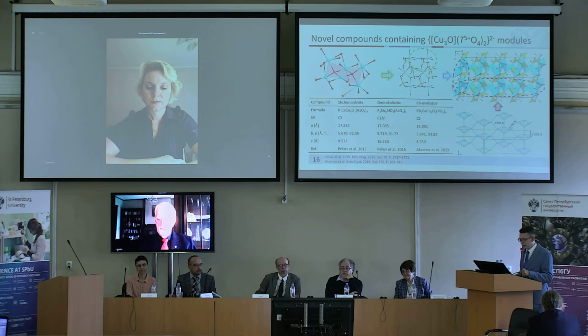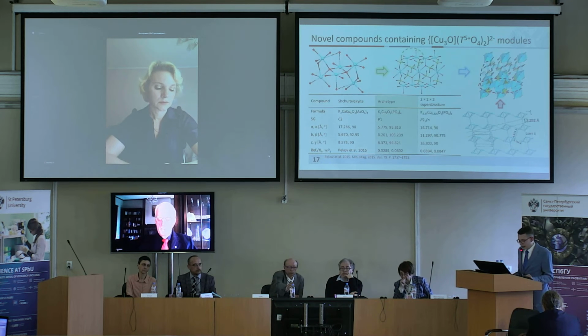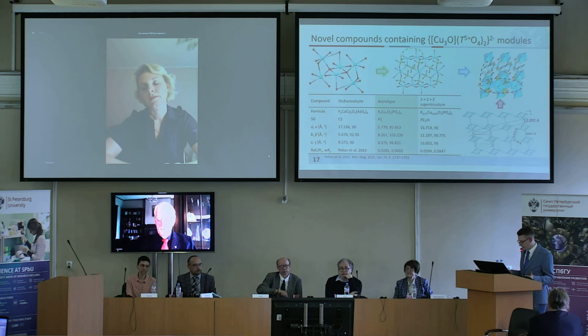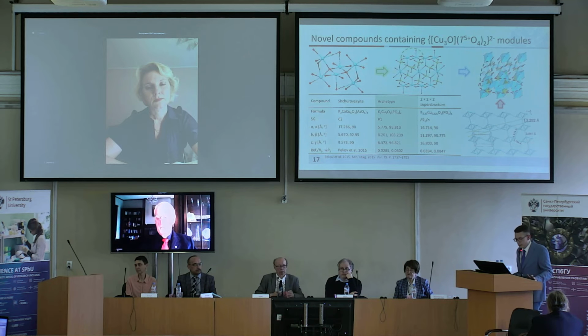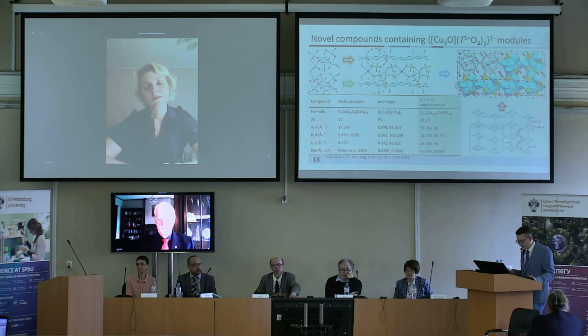And the layers are connected through either calcium atoms in Shchurovskite or potassium atoms. However, the arrangement of the dimer chains within the layer can be different. For example, in our compound, which can be called the archetype, the chains are located differently, and the layers are joined not through calcium but through additional copper atoms, which results in a copper phosphate framework lattice.